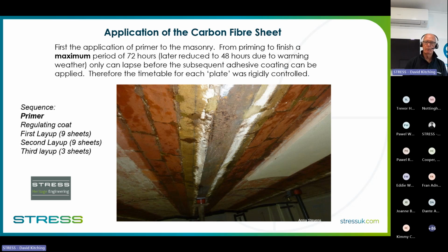Now, you would think, yeah, brickwork looks pretty all right. We're going to wallpaper it with carbon fiber. It'll be absolutely fine. But actually, when you put a straight edge to that brickwork, you'll see there's 2 or 3 mil here between brick levels, a little bit of mortar pointing sticking out. And actually, in relative terms, it's a bit higgledy-piggledy. Carbon fiber, unlike wallpaper, won't drop round little cracks and bond right to it, it will bridge those cracks. And as soon as you bridge anything, then you haven't got full bond, and you're not going to then mobilize the full 100% of the area of the carbon fiber. So everything has to be smoothed out.